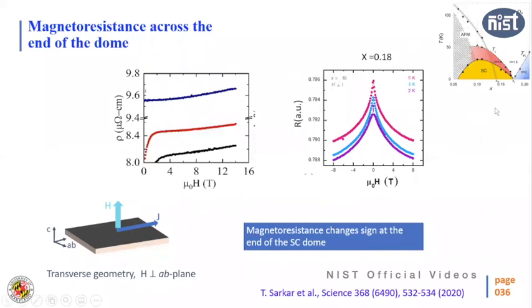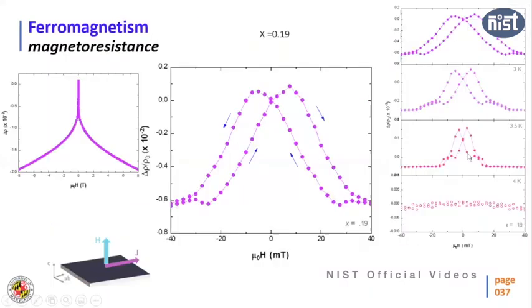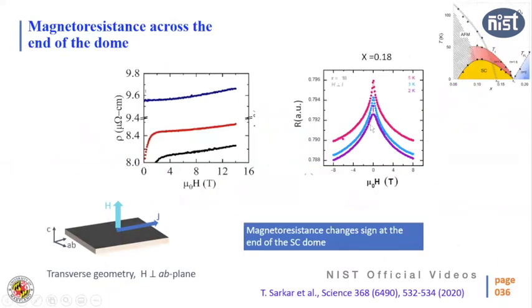When I did the magnetoresistance measurement, as we have seen for all these three samples, the 15, 16, and 17% samples, this is the 17% sample. What we found is that the magnetoresistance is positive. So if we increase the magnetic field, resistance is increasing. Now what happens when you cross this dome? The magnetoresistance becomes negative. So there is a dramatic shift. There's a big change. We measured this low field regime. I did this quick scan. We found that there is a negative magnetoresistance.